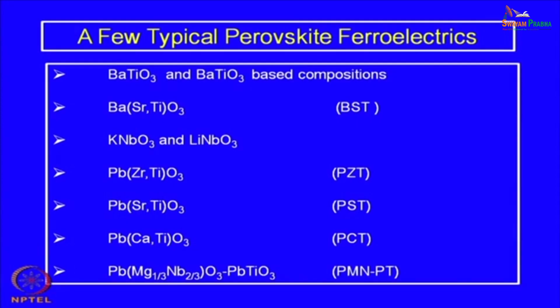In short, compared to barium titanate, the susceptibility peak or the dielectric peak is a little different. It is a little broad peak, and it also depends on the frequency. So, it is a frequency dependent peak. The mechanisms are slightly different, and it has a much broader peak. Instead of a single relaxation time, there is a spectrum of relaxation times, and as a result you have a much broader peak in this group of compounds.